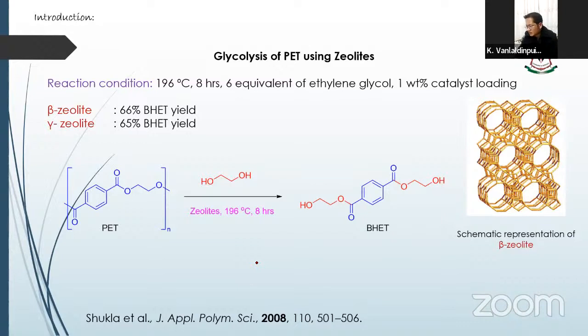And they have a microporous structure. We can see it here also, in this schematic representation of beta zeolite. So they have a microporous structure, and they are mainly used as an absorbent and as a catalyst for different types of transformations. So when we employ these zeolites as a catalyst, the reaction was carried out at 196 degrees Celsius, and after 8 hours of reaction time with 6 equivalents of ethylene glycol and 1 weight % catalyst loading, beta zeolite gives 66% BHET yield, while gamma zeolite gives 65% BHET yield. So these are some of the results which have been obtained by the international community.